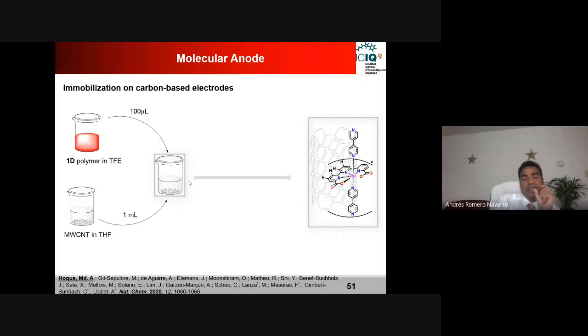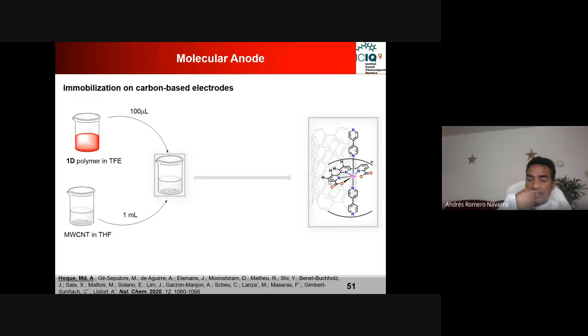Once I mix them, what I saw is the immediate disappearance of the color when we're mixing here. What it is indicating is that all this red color compound is anchored onto this multi-wall carbon nanotube surface, and the amount of this carbon nanotube is way higher than the catalyst, and that is why it is not visible. So it means all the soluble polymeric compounds get stuck onto this carbon-based material, and here I'm showing that it looks like that.